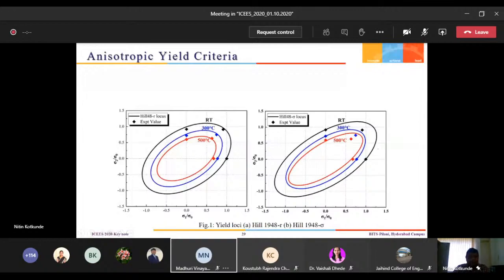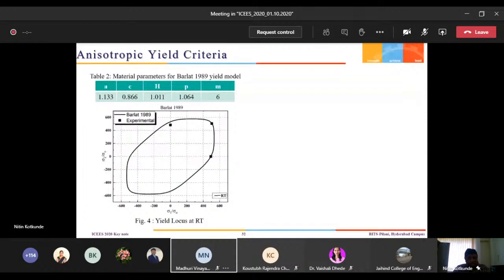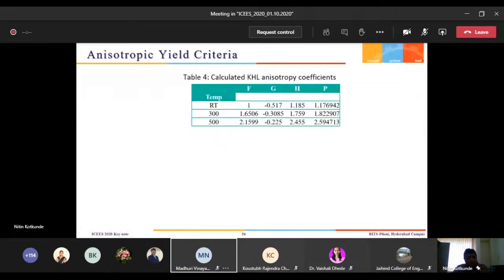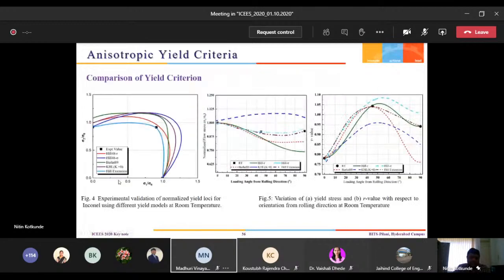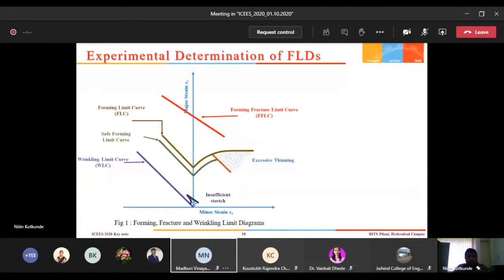Similarly, we have developed the Barlat 89 yield criteria, and these are the constants; it is also predicting very well. And then we have developed the KHL model also. So these are the 3 models if you compare, then Hill extension also we have developed. So overall, by comparison of all models, we realize that the Hill extension fits very well, because we also need to check the yield stress variation with respect to rolling direction and the anisotropy coefficient variation with respect to the rolling direction. So based on that, we realize that the Hill extension is the best anisotropic yield criteria, which we can use for the numerical studies of sheet metal forming applications. Then we come back to the FLD experiment.